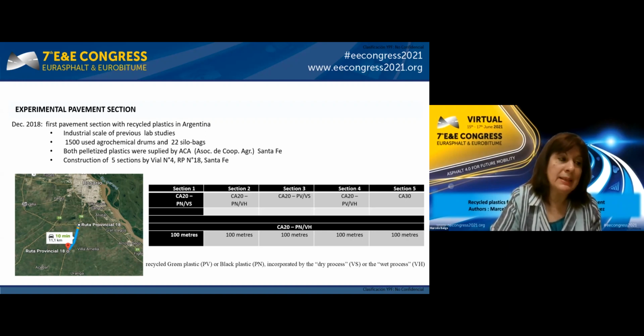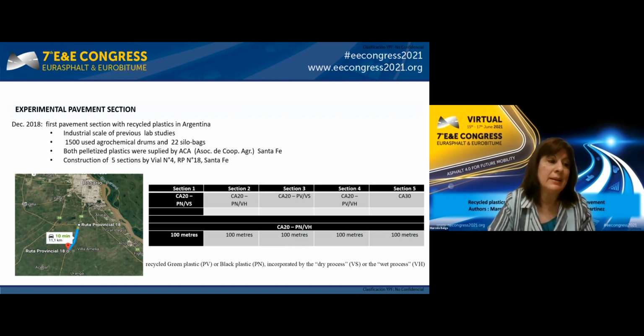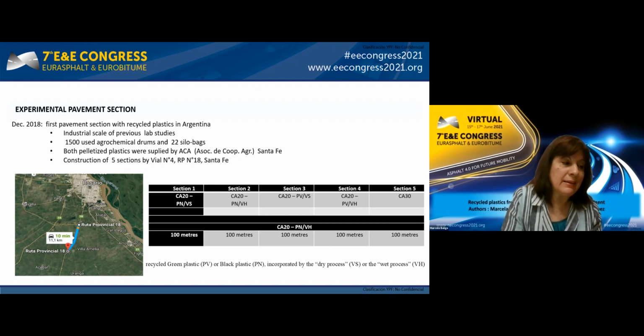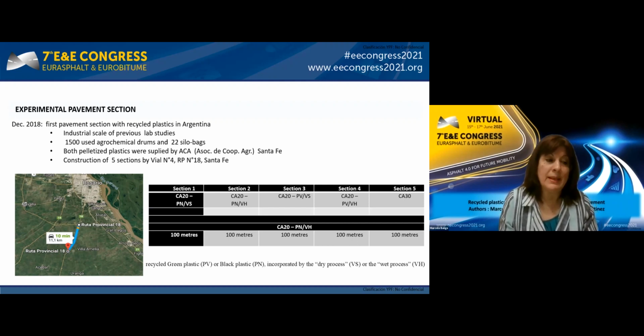scheme, of 100 meters each, were built using modified bitumen with either recycled green plastic coded PV or black plastic coded PN. The process used to incorporate the mentioned recycled plastic is identified in the graph either as VS when the dry process was used or VH when the wet process was used. You will also see that the 5th asphaltic section of the descending line at the extreme right of this graph used a conventional CA30 bitumen. This section was selected as the reference pavement of this experimental work.